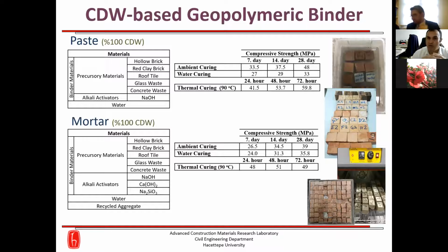Our purpose is to develop a new material with 100% construction demolition waste, only including CDW. So firstly, I think 2 years ago, we started to develop different kinds of binder from our materials. And we studied paste specimens without aggregate, and we obtained our best results at around 60 megapascal. Here, you can see 59.8 megapascal under 72 hours at 90 degrees centigrade thermal curing. That's good, but it is a thermal curing process we do not prefer, and it's not possible to use this thermal curing process in real field application.